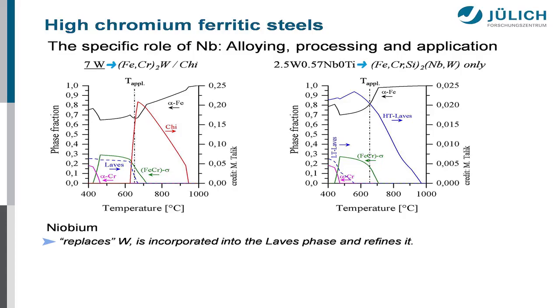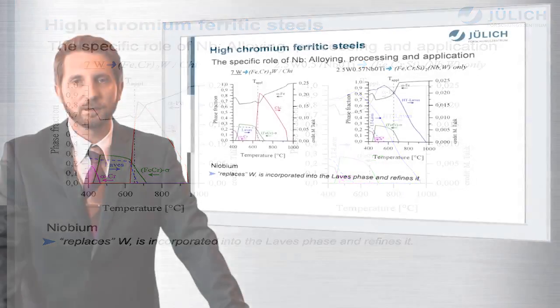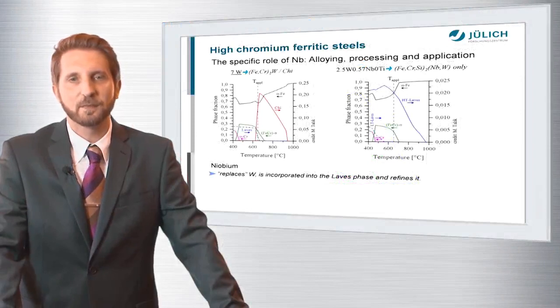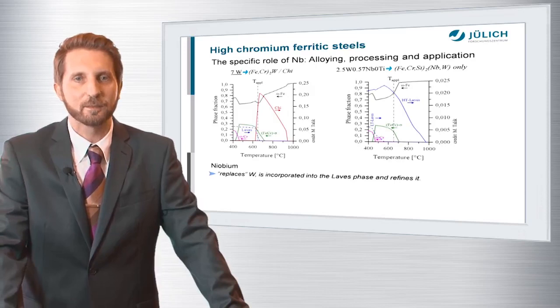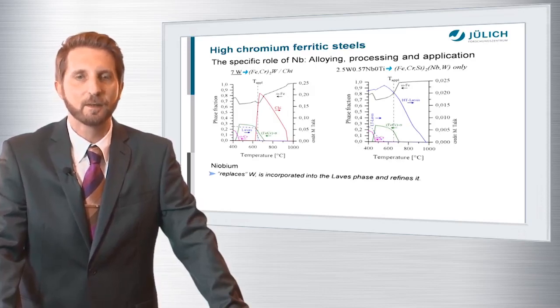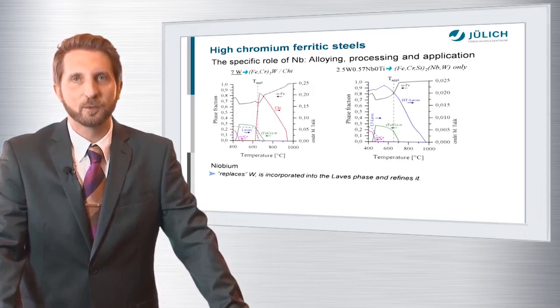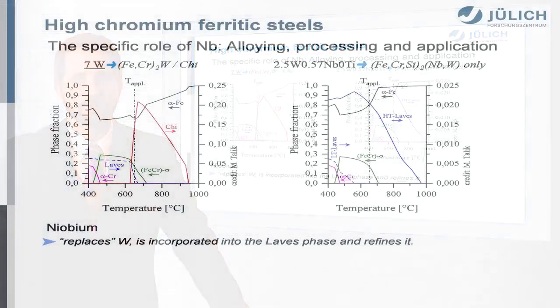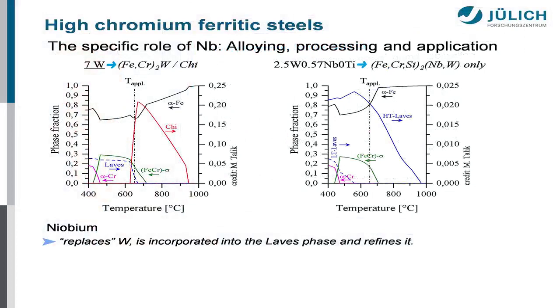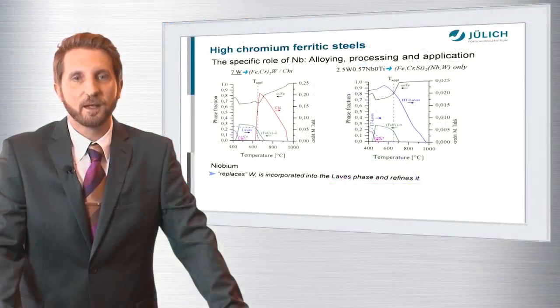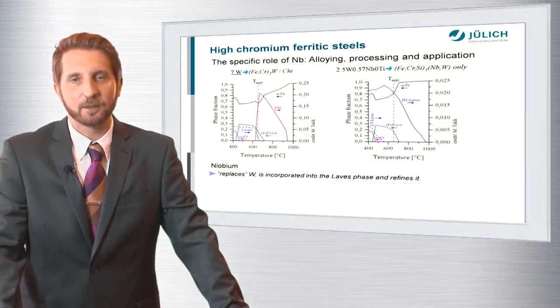So what is the specific role of niobium in these alloys? To give an answer to this, we have to have a look into some simplified phase diagrams, but I'm not going very deeply into detail. So to keep it simple, if you want to go for strengthening a fully ferritic steel by intermetallic phases, and if you just want to do it by simple tungsten alloying, you have to go up to a tungsten content of approximately 7 weight percent to reach sufficient creep strength or reasonable creep strength. And that means that such an alloy would be, on the one hand, very expensive. On the other hand, it will be hard to process. And if you think about weldability, such a high tungsten alloy should be a nightmare.